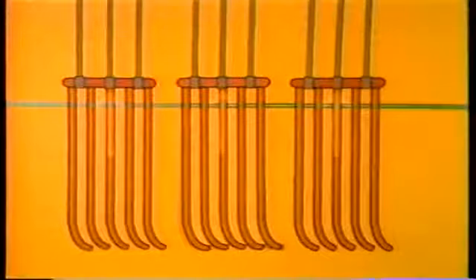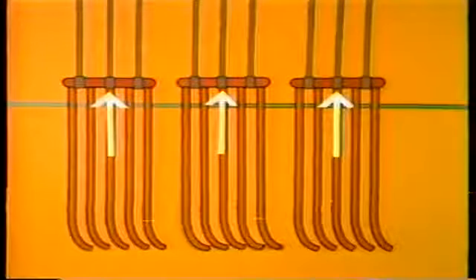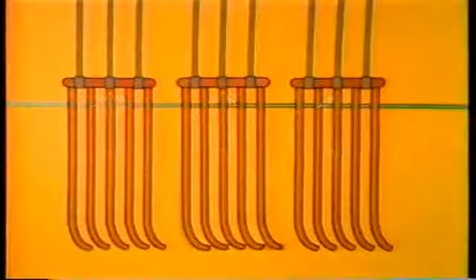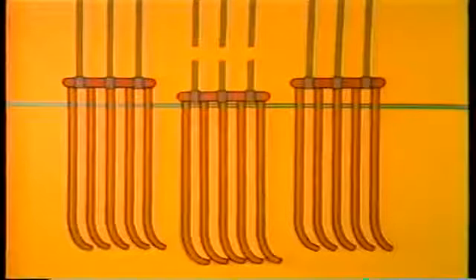Another general problem in superheaters is support failure. Watch for support failure when inspecting the superheaters. Total support failure is a very serious problem because it can lead to collapse of the superheaters. Pendant and platen superheaters are suspended from the top of the boiler. Each tube element is attached to headers located outside the hot gas path. The headers have their own supports. If the header supports break, you may not be able to see the break itself, but you will notice that the superheater tubes are out of position.